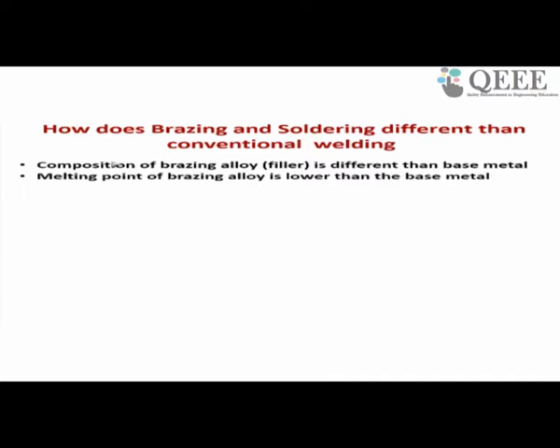However, in brazing and soldering, the melting point of the brazing alloy and solder alloy is very low as compared to the base material. That is one difference. The second one is that conventional welding means I am talking about fusion welding. In fusion welding, the welding is happening because of melting and solidification of the base material. However, in brazing and soldering, the joining is happening because of capillary action.